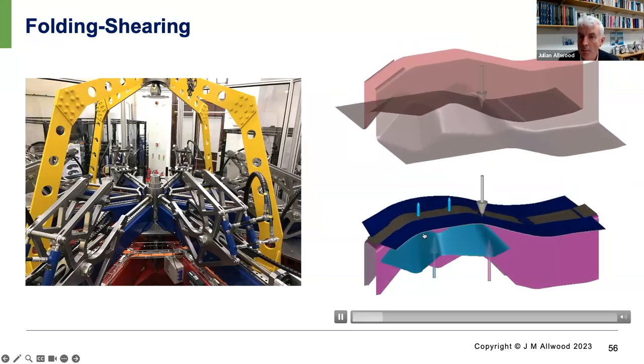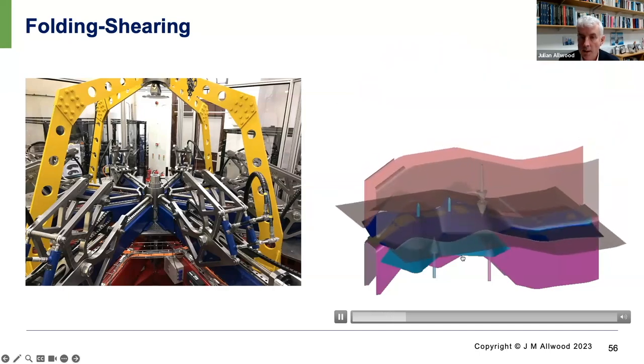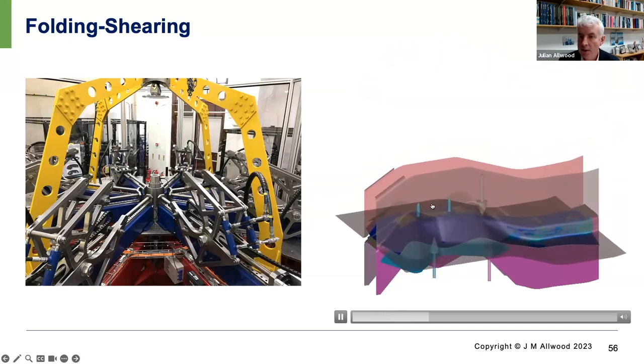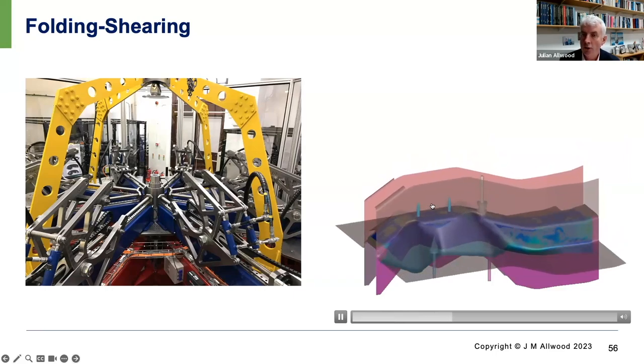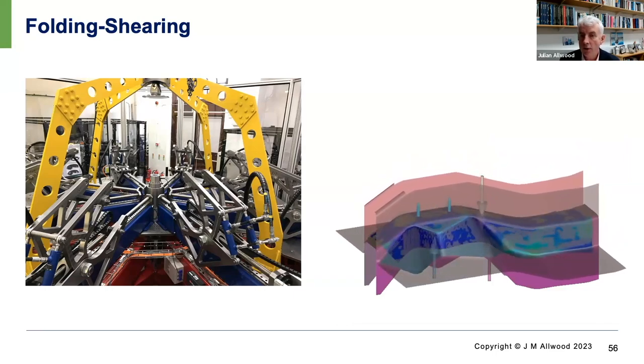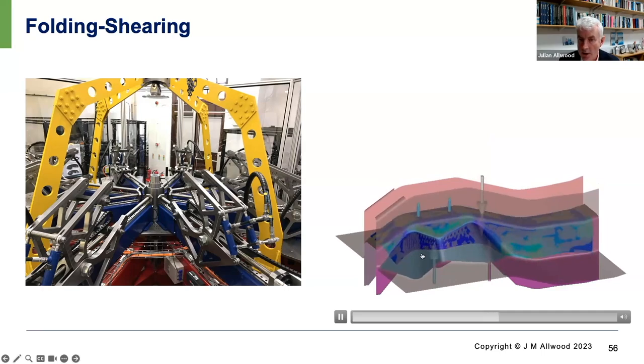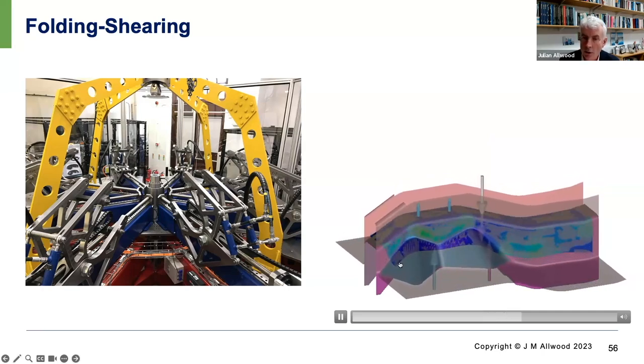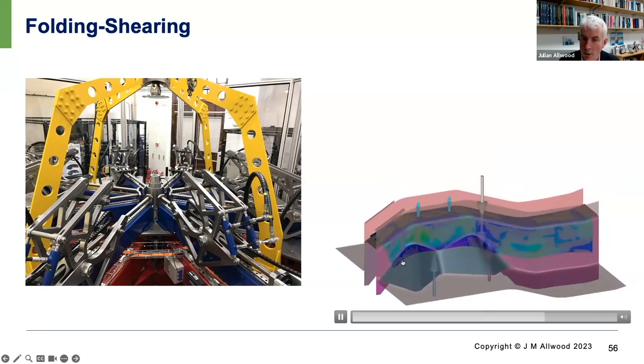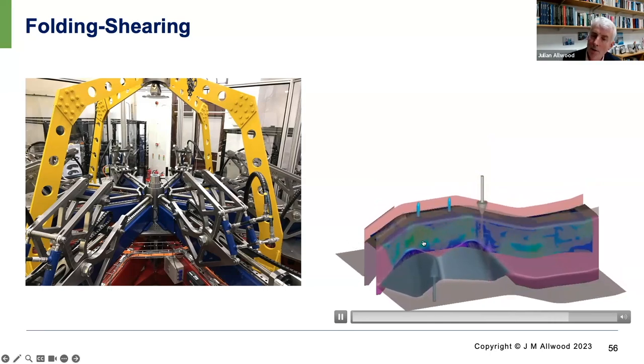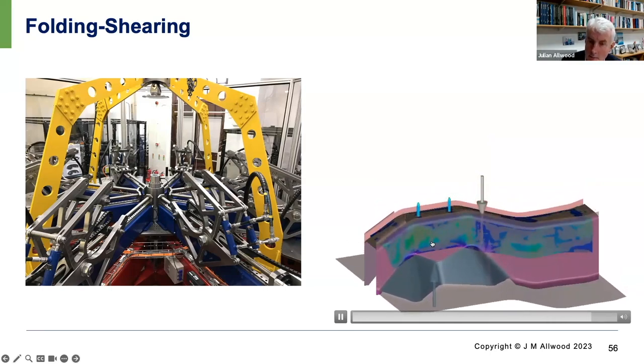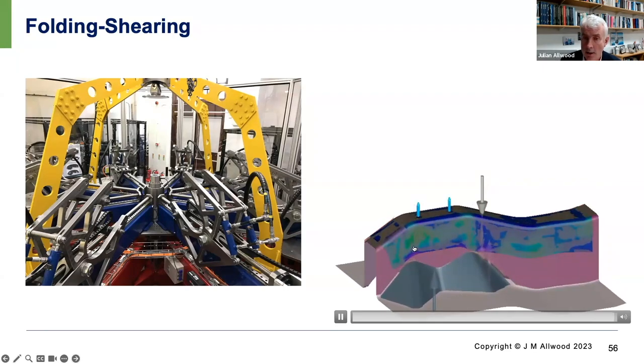The dark blue is the workpiece. Then the upper tool firstly creates folding, no shearing yet. And now we've finished the folding, and here comes the shearing stage with the material held loosely between an upper and lower cone. And that creates very nearly pure shear in the side of the sheet, leading to almost no change in thickness and the finished part with almost no trim.